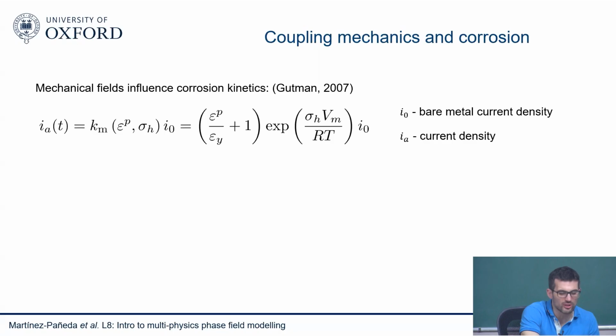And this has been reported many, many times in experiments. Sometimes you see it, sometimes you don't see it, so it's a bit of a complicated thing. I don't think it's fully understood when you see it and when you don't see it. One thing that we know is that we do see it under conditions of activation control corrosion only. When you have diffusion control corrosion, mechanics doesn't play a role.